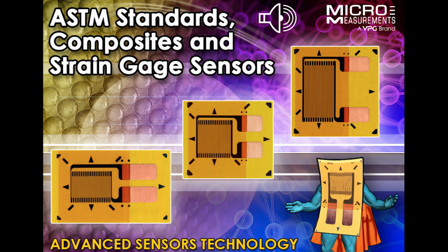The reason why in flexural there are several cases where we use a strain gauge based transducer to measure it, like a deflectometer, is that we would literally put it underneath the specimen. One of the issues you sometimes get with putting a strain gauge in composite flexural tests is buckling issues or tension issues right at the loading nose area. So you cannot put the strain gauge where the loading nose is, so you would have to put it on the opposite side. A lot of times you'll have premature breakage of the surface fibers, so unless you're measuring a really short section of the flexural part, it's usually easier to put a deflectometer underneath there. Less danger of breakage or bad readings.